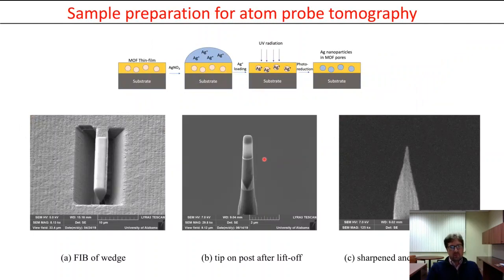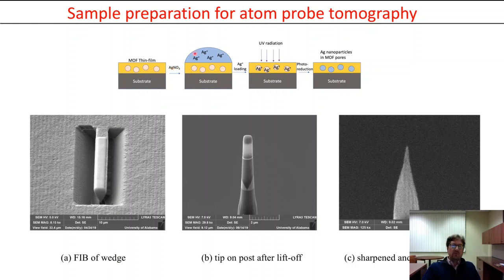We are currently using these thin films as a host to synthesize nanocatalysts. We have a thin film representing the nanopore and we intercalate silver ions into these pores by dipping the film in a silver nitrate solution. After loading the pores with ions, we rinse, place the film in a methanol solution as a sacrificial reducing agent, and use UV light to transfer an electron from the methanol to the silver ions, reducing them to make silver nanoparticles. We then need to characterize these sub-nanometer pores using atom probe tomography.